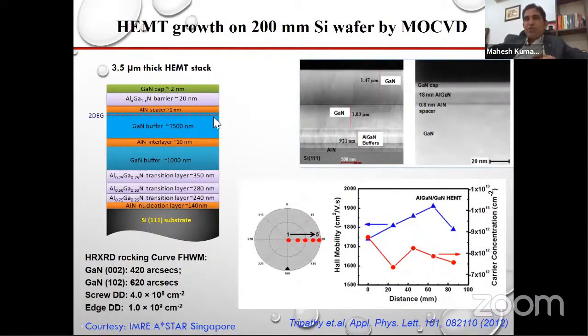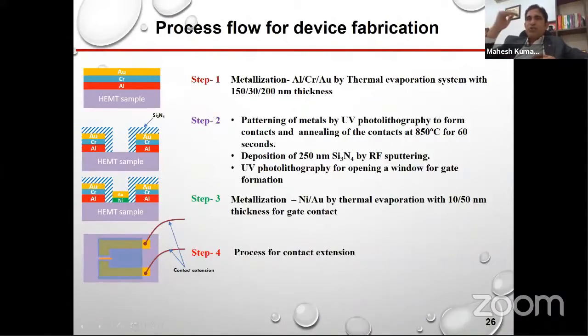Now, how to make the contact? On the aluminum gallium nitride, we can deposit aluminum, and if you do the thermal step, RTA, rapid thermal annealing, this aluminum will diffuse and make contact with the 2D electron gas. So we have used aluminum, chromium, and gold, and then by lithography we opened this window, and by RF sputtering we have deposited an isolation layer, isolating the source and drain. Otherwise, when we dip in the water, the source and drain can short.